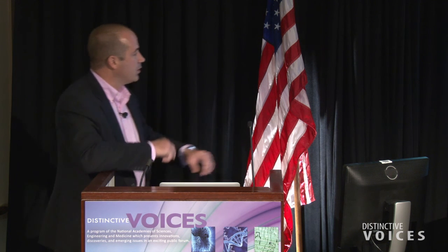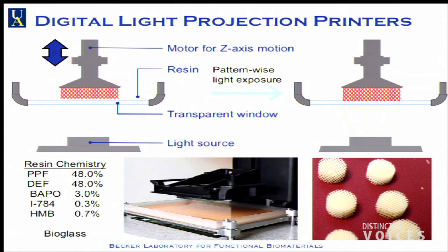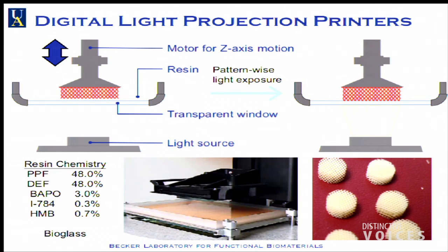Now, how 3D printing works photochemically. And again, this is about as simple as you can make. You have a resin bath here, which is basically a pool of honey. You have a tub. From the bottom, you have a light source, the same light source that you find in your LCD television or LCD projector. It projects through a transparent window. You have a motorized axis, and then you have an oxygen depletion zone very near the window. You get a focal plane, an in-focus image that will print and turn that honey into a solid. And then the motor pulls it out, so you're growing from the bottom. You print here first, and less up here.